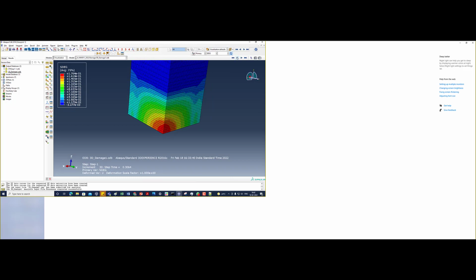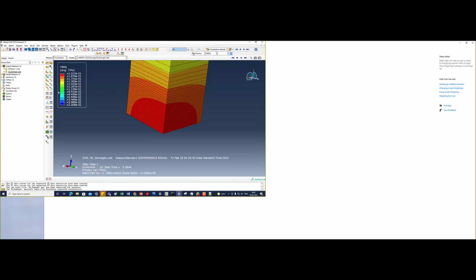Okay. So this is where it is started from. So in this frame you see there is 0 value, and then now you see some value, right? And the red one will be somewhere, but the yellow one is 0.01. So our starting point is how much? 0.05, no? So if you look at equivalent plastic strain, so that has a value of 0.2. And just before this, still there. So damage must have initiated when the value was 0.05. So at this point of time.